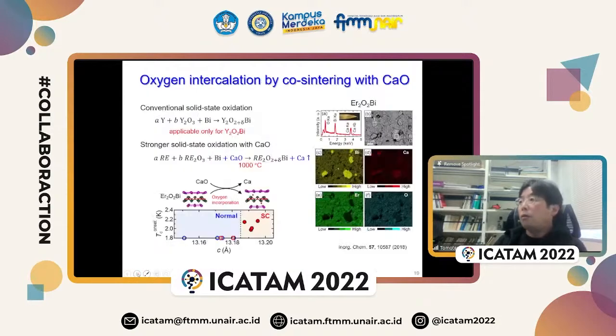So we tried to make other layered compounds by using a similar method. In the case of Y2O2Bi, oxygen intercalation is very easy. By introducing Y2O3, we can introduce an excess amount of oxygen. This is easy, but for other layered oxide bismuth compounds, this is not applicable because excess oxygen is difficult to introduce in these compounds.